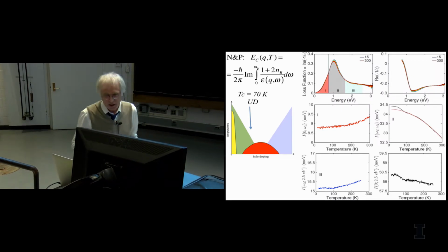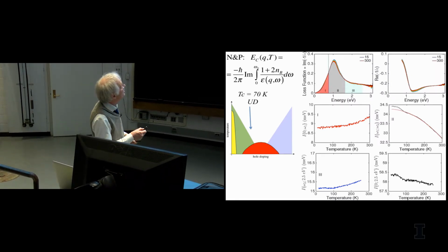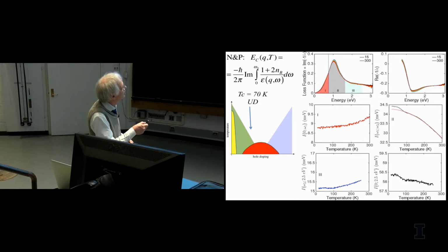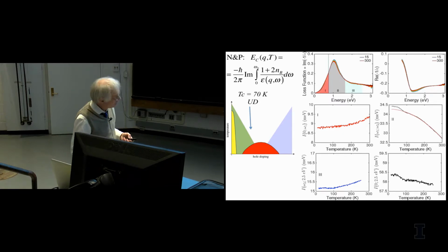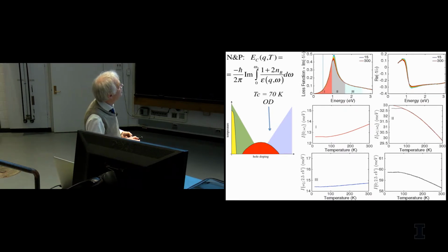Okay, so here are two examples now. This is a so-called underdoped sample on this side. If you follow the total Coulomb energy, that's this integral here, or actually the integral around the peak over here, it becomes a little bigger when you go superconducting. You can also see that there's much less intensity coming from those two wings, so the main part comes really from here. And if you go overdoped, you should look at the black line. The red line is an extrapolation. It has the opposite sign. So here the Coulomb energy gets smaller in the superconducting phase.